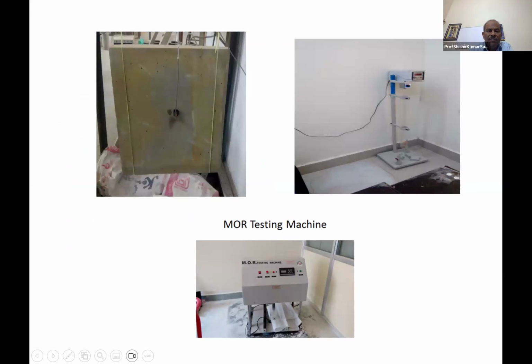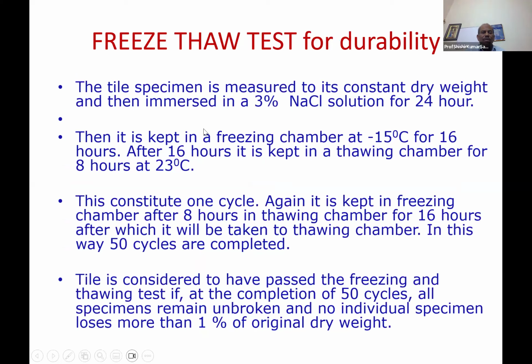Then the freeze thaw test for durability. The tile specimens are measured to its constant dry weight and then immersed in 3% sodium chloride solution. Then it is kept in a freezing chamber at minus 15 degrees for 16 hours, and in a thawing chamber for 8 hours. So freezing, thawing, 50 cycles, I think we have done. This constitutes one cycle. Again, it is kept in the freezing chamber for 8 hours and thawing chamber, after which it is taken out of the thawing chamber. So 50 cycles are completed.